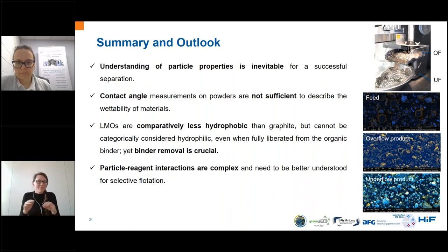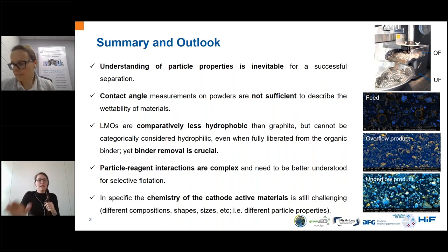Then flotation, I only showed you one reagent, but usually in the flotation you have a frother, you have a collector, which renders the particles hydrophobic. You also have depressants, which render other particles hydrophilic. So you have a lot of chemicals and reagents in there, and a lot of interactions which are really complex. You also have the hydrodynamics. You have a suspension phase. You have a froth phase. So it's really a complex process, and there's a lot of research going on in that field.